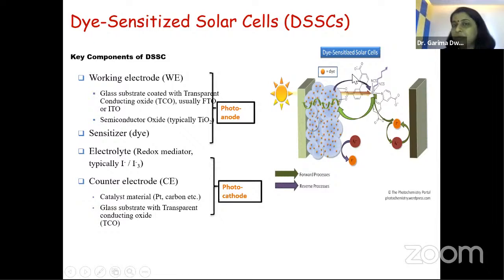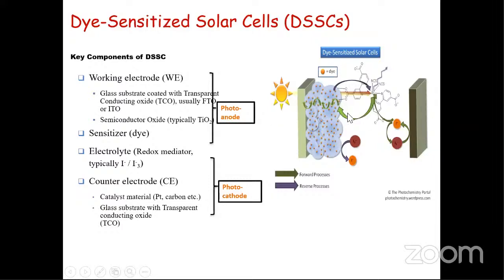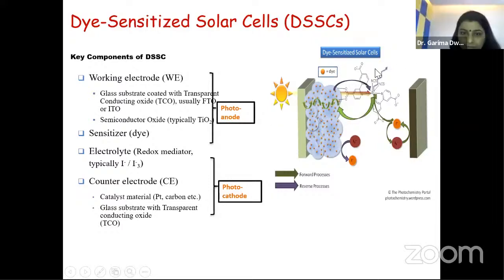In our case, we are using ruthenium dyes. If we see the counter electrode, this is also conducting glass. Both are glass. On this conducting glass, we deposit a layer of platinum, which will work as a catalyst. And in between these two electrodes, we insert the electrolyte.